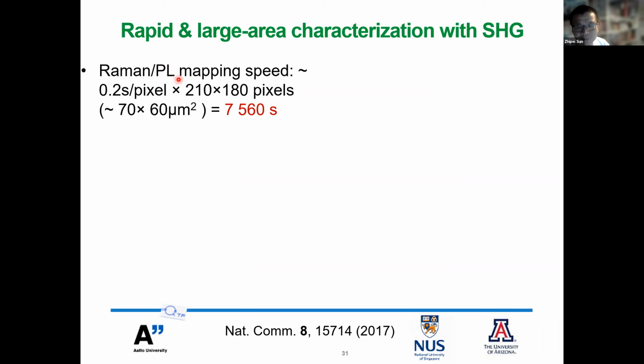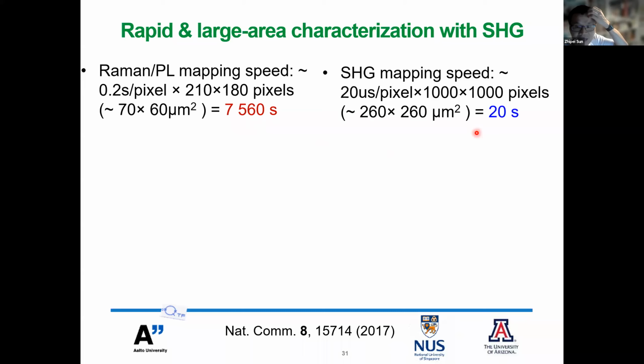However, Raman and photoluminescence typically need a very, very long time because you need to check the whole response spectrum. For example, for one Raman image of a sample around 4,200 micrometers squared, the time we need in our lab is around 7,000 seconds. But with second harmonic generation and third harmonic generation, it is much, much faster because you don't need to measure the whole spectrum. For a much, much larger sample, the measurement time is around 20 seconds.